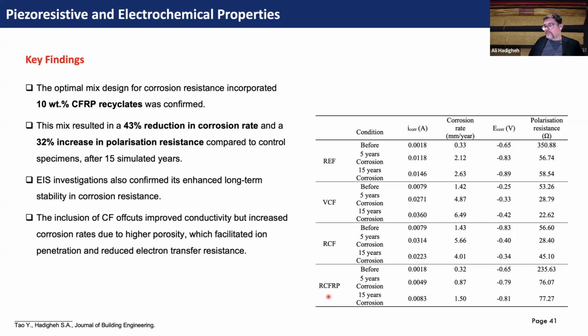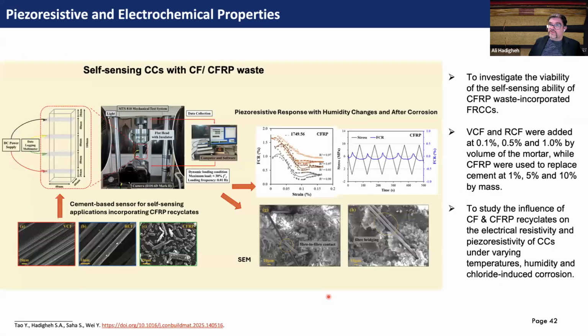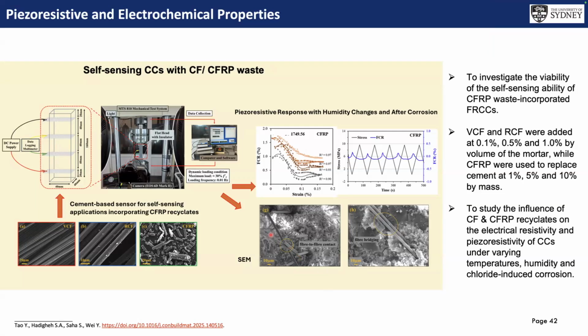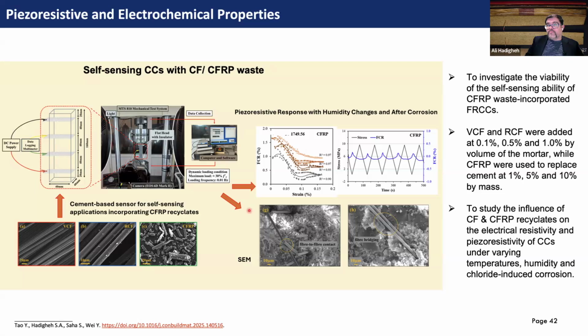So these are the things that we need to consider when we are dealing with incorporation of these materials in concrete. But in terms of that self-sensing that we were talking about, again, we did these piezoresistivity tests, and we looked at when we incorporate these composites into concrete, both in terms of CFRP and carbon fiber, and also GFRP, how they perform, and if we can use how they respond. And we did dynamic testing